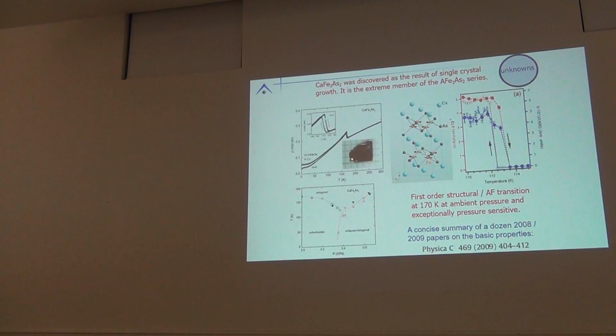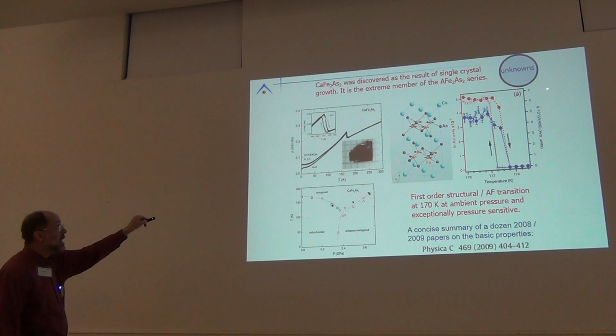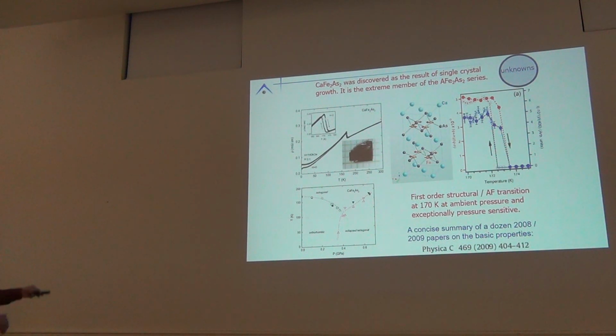Let's try calcium. We discovered a new member of the 122 series, calcium iron 2 arsenic 2. We could grow, we discovered, and it's sort of rare to discover something in large single crystalline form, so we were happy, of calcium iron 2 arsenic 2. It's an extreme example of the physics we see in the barium and the strontium. We have a strongly coupled structural magnetic transition. It's brutally first order. You can see both the orthorhombicity and the antiferromagnetism having hysteresis, having strong jumps at this transition temperature. We were able to look at the effects of pressure. We discovered a new type of phase transition called the collapsed tetragonal. It was a lot of fun. It's ongoing, actually. We'll come back to this at the very end of the talk.